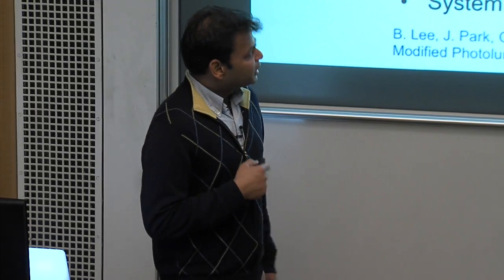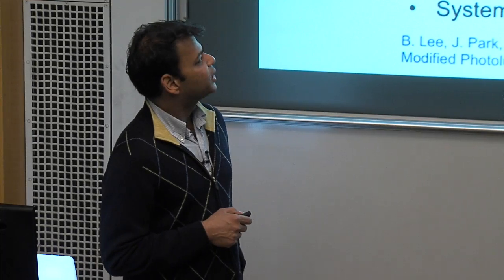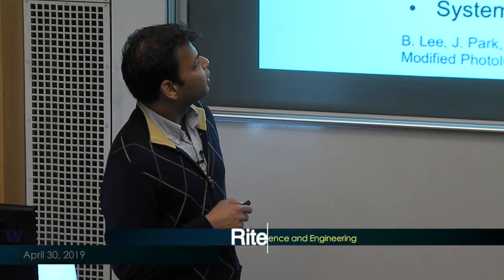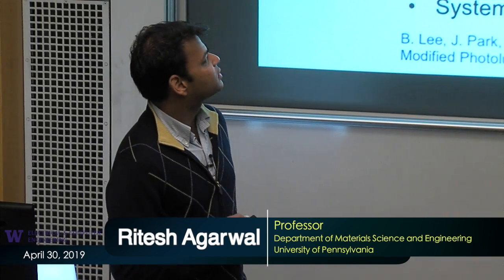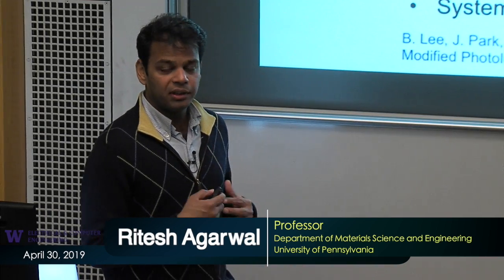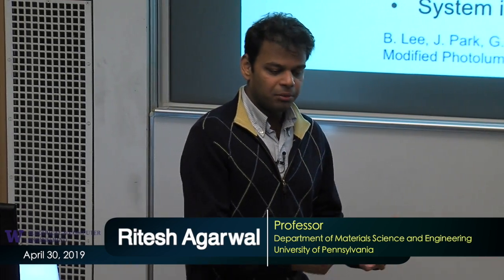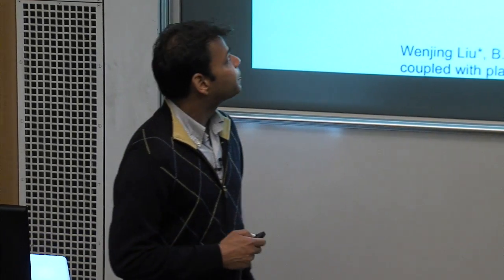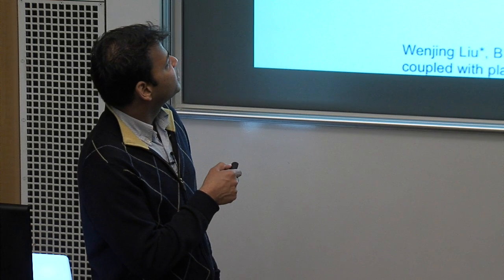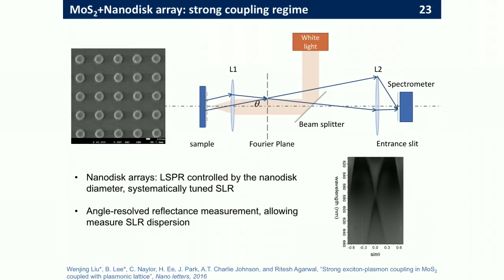This got me excited, not only because we saw a Fano line shape, but mostly because it was telling me very clearly that if we optimize and think about this more, then in principle we can take the system to strong coupling, which means we can create polaritons between the excitons in the system and the plasmons. So we moved from the bow ties to these disc type cavities, because fabrication-wise it's easier and the inhomogeneous line width is smaller.